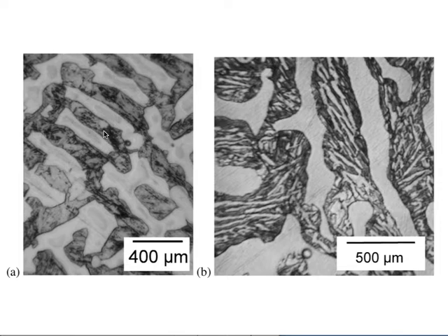Okay, so this is the as-cast microstructure. When we then heat treat it so that we have a mixture of austenite and ferrite, we can never get rid of that delta ferrite, by the way. It formed from solidification, and it doesn't matter what temperature we go, we will always have the delta ferrite there, right? But the remaining region can be austenitic, and then we transform it into a mixture of bainitic ferrite and austenite. Now, there is a big advantage of the fact that you can never make this material fully austenitic.